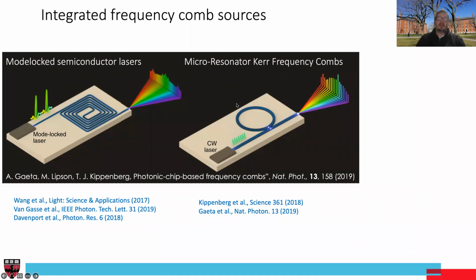And in the output, they look basically like a frequency comb. So originally, we have actually demonstrated both of these functionalities, as I'll show you, in lithium niobate. But originally, one of the first motivations for our lithium niobate platform was indeed to realize a comb using the Kerr effect, then to broaden the comb using this broadening, and eventually to do second harmonic generation to lock the comb.